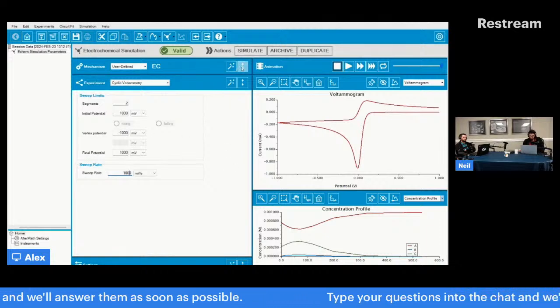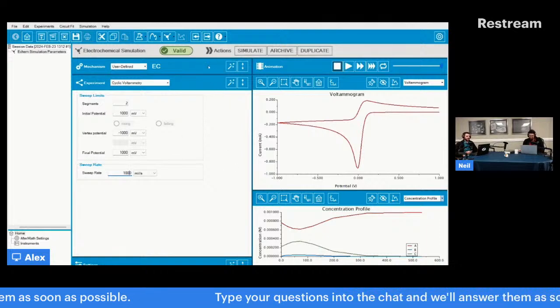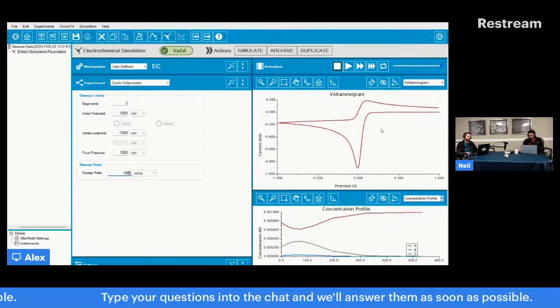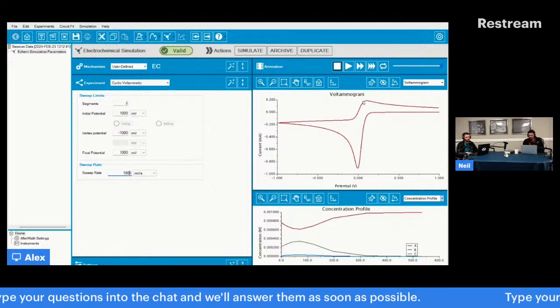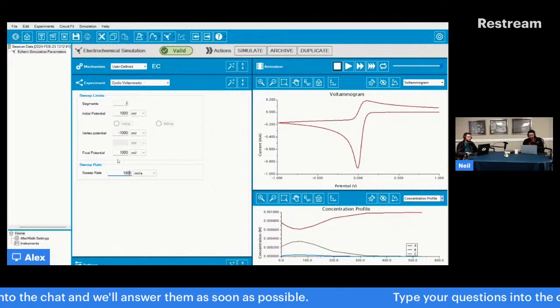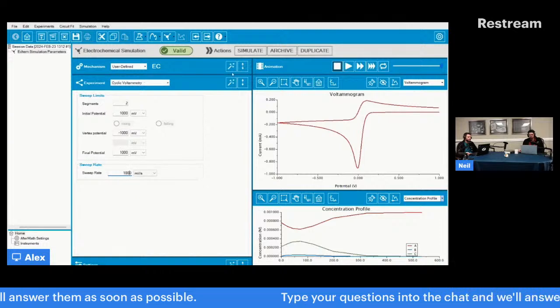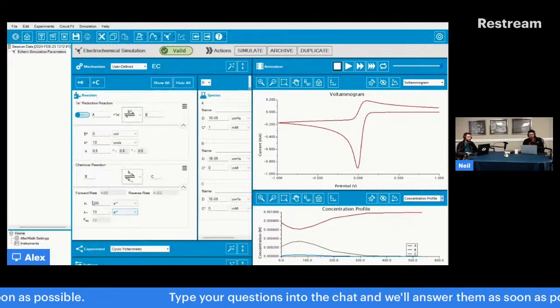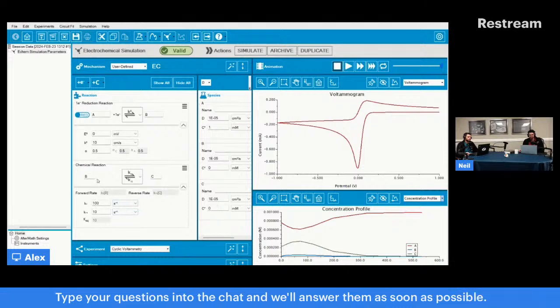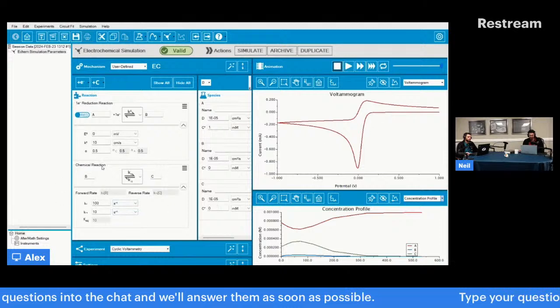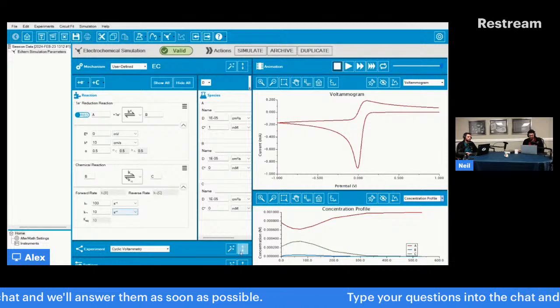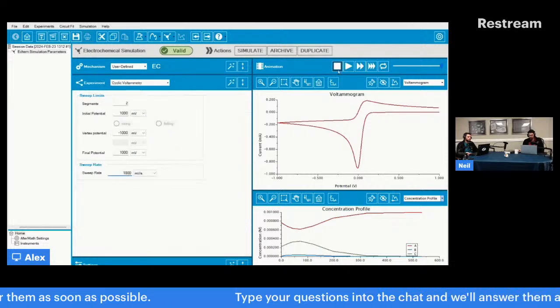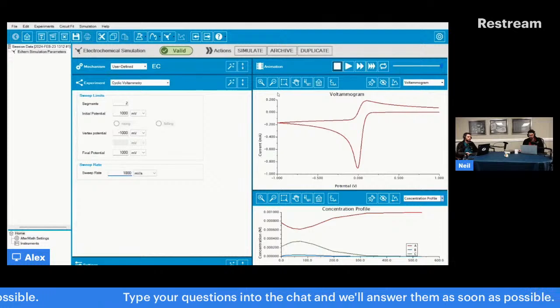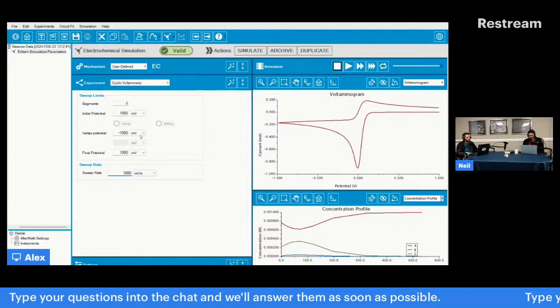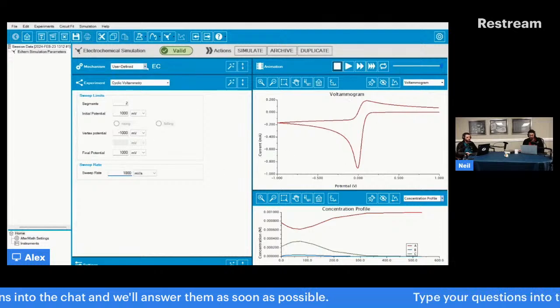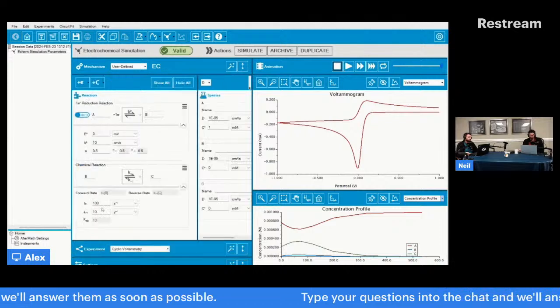This is actually not what I would anticipate because the peak is growing because of the scan rate, but no, this is because if you're sweeping the voltage fast enough, there will not be as much time for this reaction to go. So in principle, as you scan faster, you should observe that it actually looks more like a normal voltammogram. That's normally what you would observe for an EC reaction.